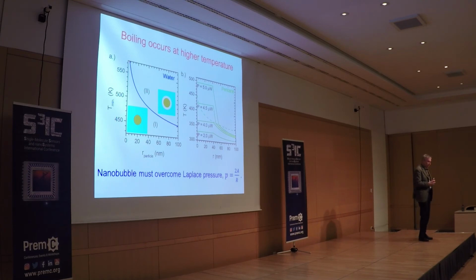But if you do the same experiment now around the gold nanoparticle, the first bubble that you have to create, as shown here, is quite small. It's nano-sized, a sub-micron size, typically a few tens of nanometers in radius. And that means this very small bubble has a huge internal pressure. That's the Laplace or Laplace-Young pressure, which is due to surface tension. And because we are still far from the critical point, this surface tension is pretty high. So this added pressure, twice the surface tension divided by the radius, because the radius is so small, is typically several atmospheres, 10, 20 atmospheres. So this means that it's like in a pressure cooker.